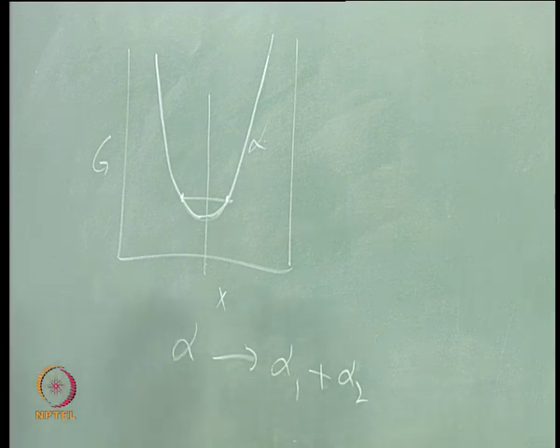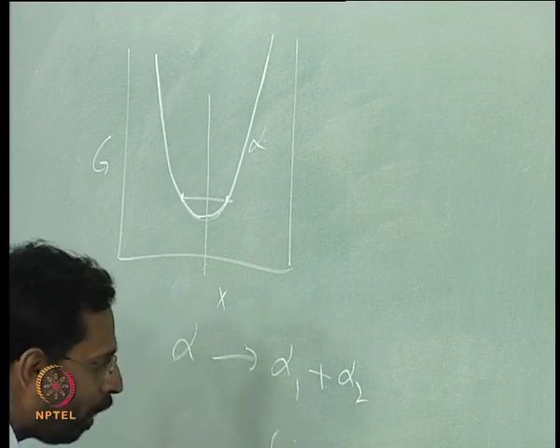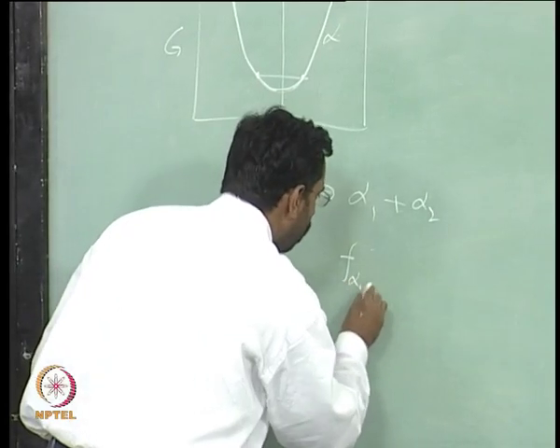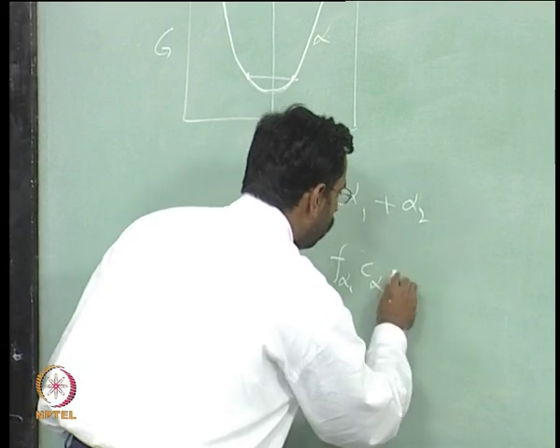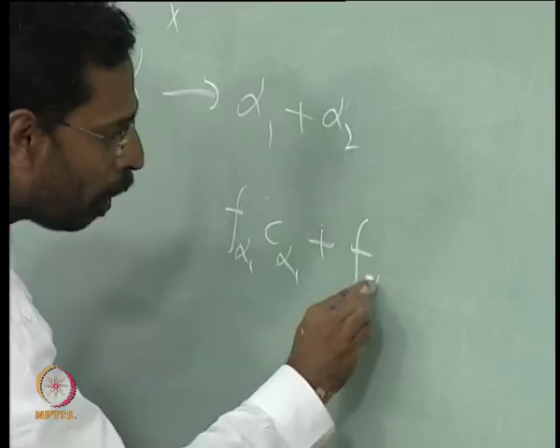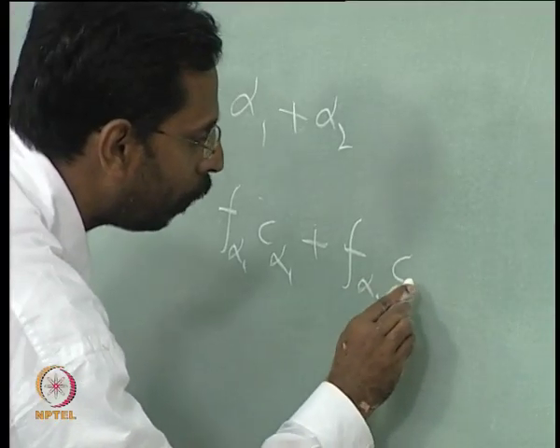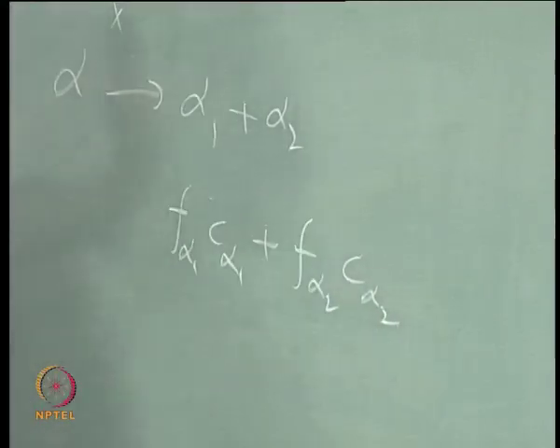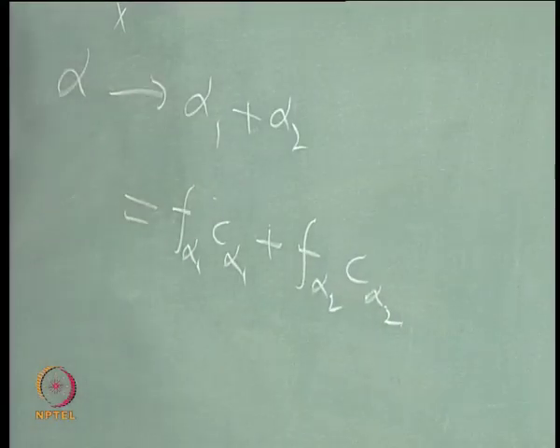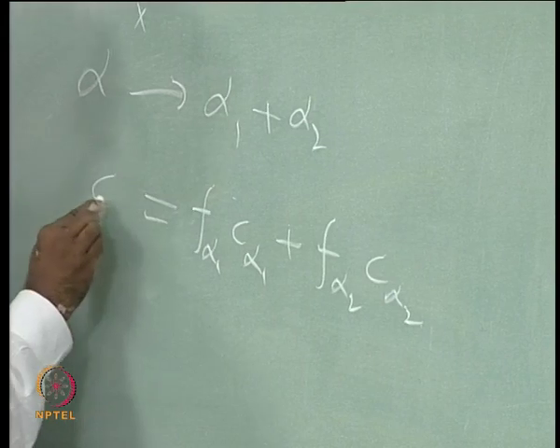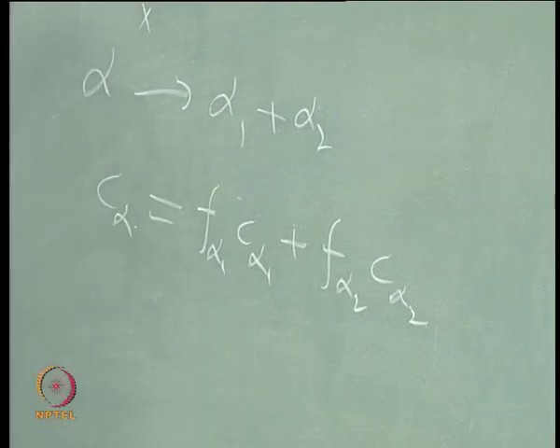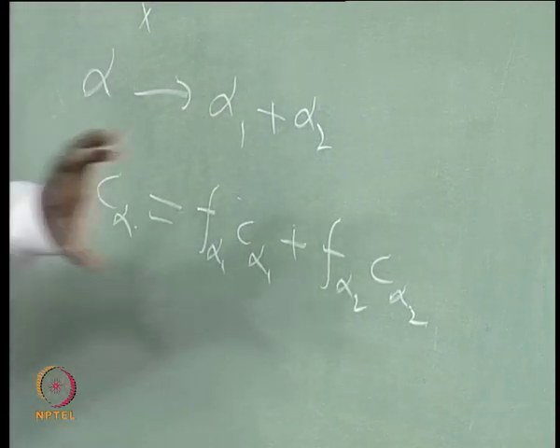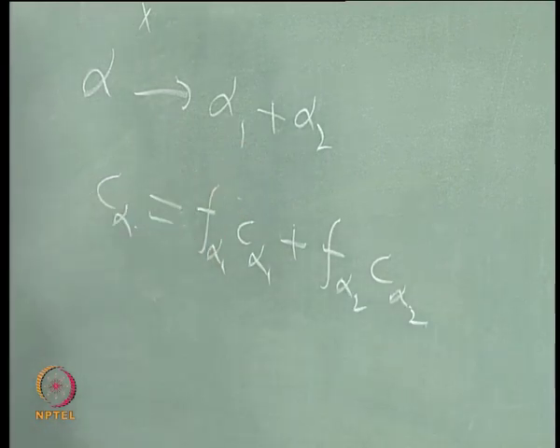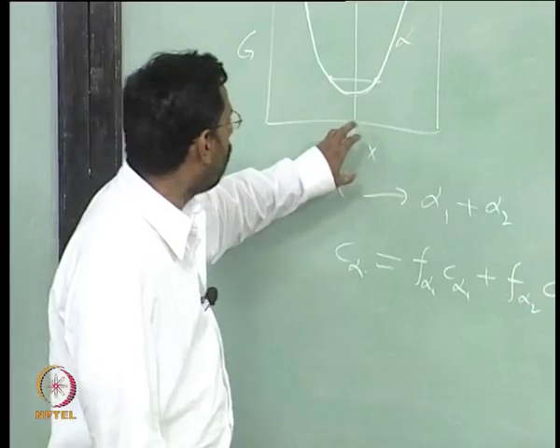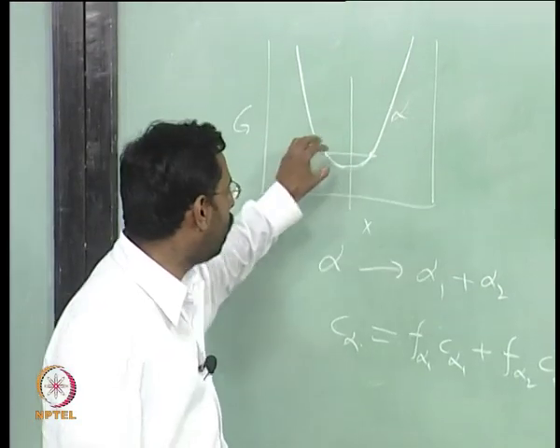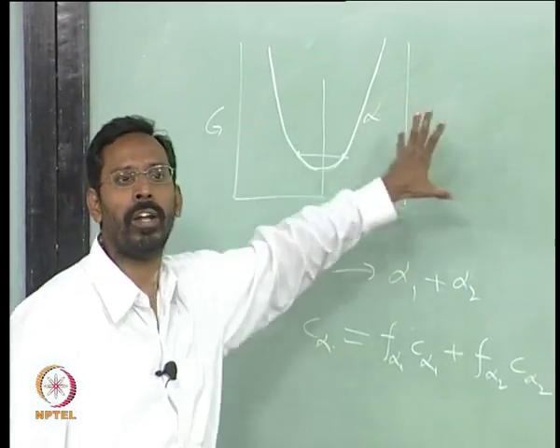That means, if I take the volume fraction of alpha 1 multiplied by the composition of alpha 1 plus volume fraction of alpha 2 multiplied by the composition of alpha 2, it should be equivalent to what? The composition of alpha with which I have started. This is the mass balance. As long as the mass balance is maintained, the alpha splits into some part of alpha 1, some part of alpha 2.